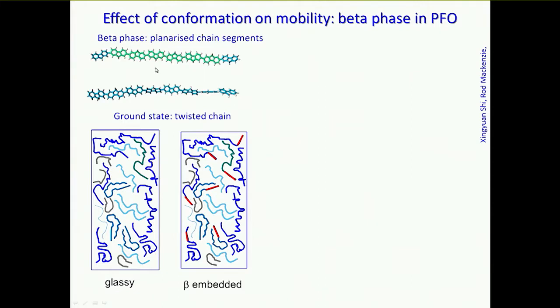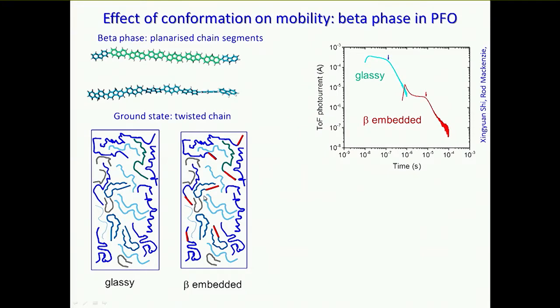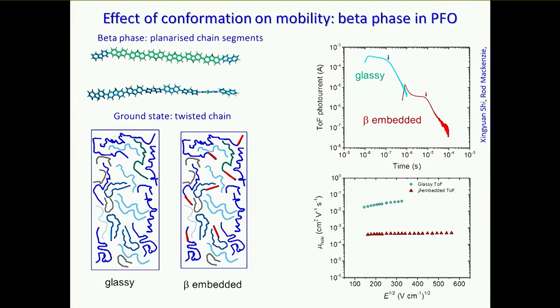So we know how to introduce beta phase, we know how to keep it out, let's have a look at what happens to hole transport in the presence and the absence of beta phase. So we do the measurements. One of the most reliable measurements to access hole mobility, or this is what we thought anyway, is a time-of-flight photocurrent measurement, where you excite your film with a pulse of light, it sets up a transient photocurrent, you measure the time at which the charge reaches the other side, you work out from that velocity and hence mobility.